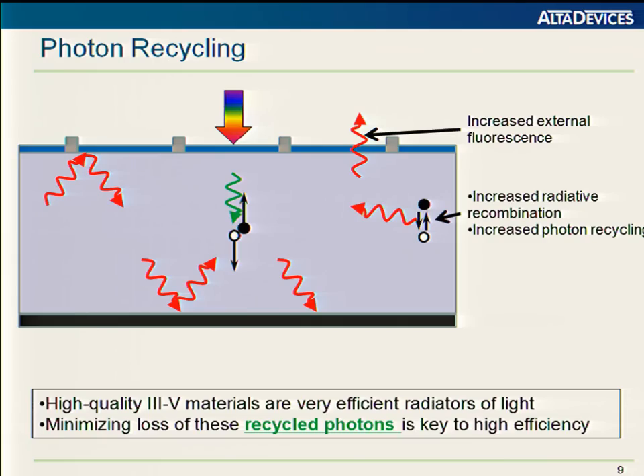You have a much better chance, A, of collecting those carriers, so that's a JSC boost, but you also increase the carrier density within the cell, so it affects the voltage of the cell. In these materials, because they're limited by radiative recombination, the lifetime is essentially set by the doping level. For a gallium arsenide cell, for dopings around the 10 to the 17 mark, you get bulk lifetimes around 50 nanoseconds. But if you have very efficient photon recycling, this can be higher by a factor of 10 or more, because the lifetime is now extended by this photon recycling.